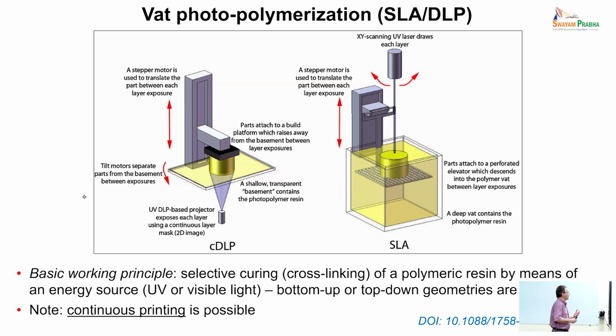And another approach is to do the same. So you're basically cross-linking your part layer by layer using a photopolymer, and you lift or lower your body by the thickness that you want for generating the layer. And then you irradiate using a different approach that is based on mirrors and a different source for the light. And the difference between these two technologies is related to the speed, the size of the vat that you can use, and for instance, SLA can typically be larger than DLP vats. But the main difference is the surface quality.